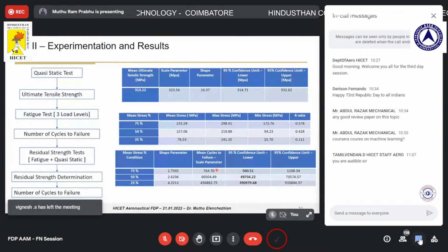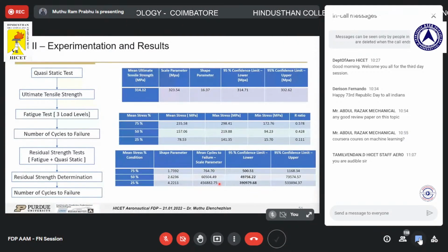So if you see, these are the mean cycles to failure for the 3 different load conditions, and under fatigue, composites will have different values. Like one sample will fail at 10 cycles and another sample will fail at 500 cycles. That's a common property of composites. So you always need to test a lot of samples to get more data.